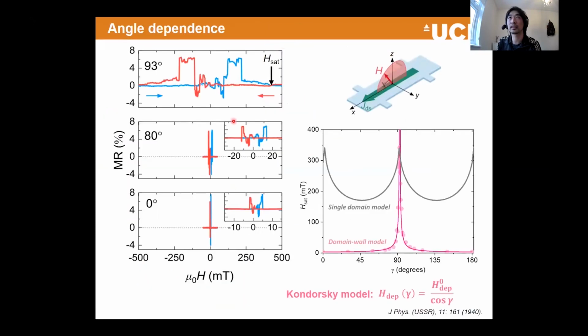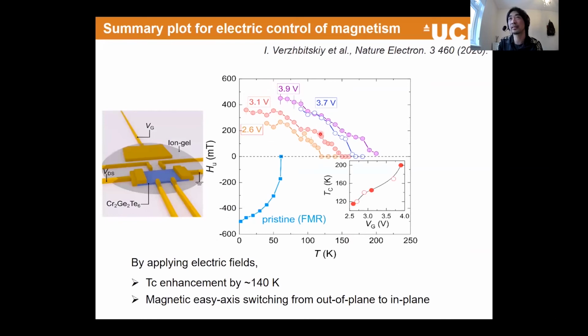One thing I just want to mention is that from now on, this magnetic field point where this switching is completed is something related to the magnetic anisotropy and something related to the magnetism. So that's a plot of this data. You can see the pristine material without gate voltage. This TC dies out around 60 Kelvin. But once you increase the voltage, we can see that this parameter goes up to a really high value. One thing we can tell is that this is changing sign, which means that the easy axis is also changing from the out of plane to the in plane. If I have time, I can discuss a bit more later.